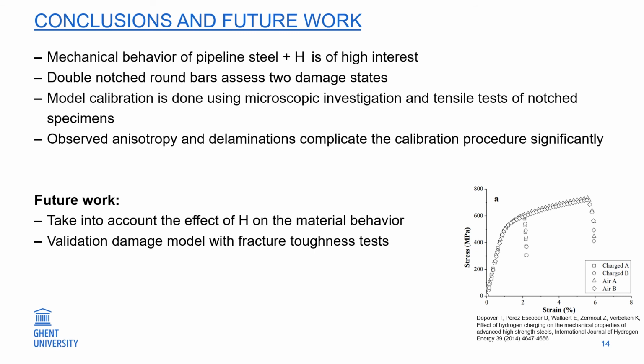In conclusion, the effect of hydrogen gas on pipeline steel is of high interest nowadays. By using double notched round bars, we can assess two damage states with only one tensile test. We will perform model calibration by microscopic investigation and tensile test of notch specimens. The delamination and anisotropy that were observed during the tensile test complicate the calibration procedure significantly. In the future, the effect of hydrogen on the material behavior will be evaluated and the damage model will be validated using fracture toughness tests.